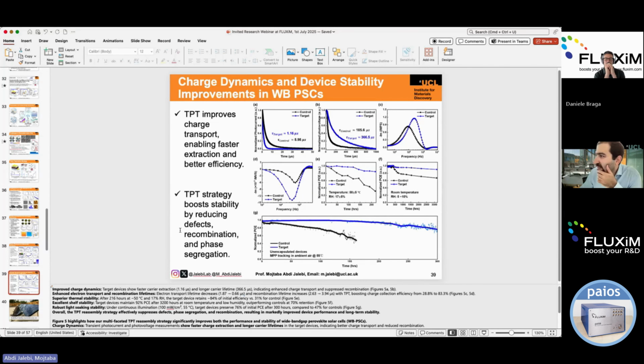Yes. For the TPV, TPC, so basically using the Paios, it helps us to differentiate these. We think it helps us to reduce traps, not only at the interface, but also in the bulk. From TPV and TPC, you can see we have a higher lifetime of the carrier. That means we reduce bulk traps or non-radiative recombination. On the other hand, we have faster carrier transport, because these are all device measurements. And the IMPS and IMVS help us to understand a faster charge collection efficiency. The indirect meaning of that is that we have lower trap density at the interface as well, which leads to faster charge collection at both electron and hole